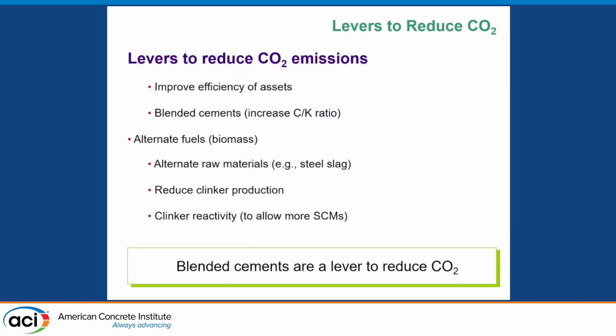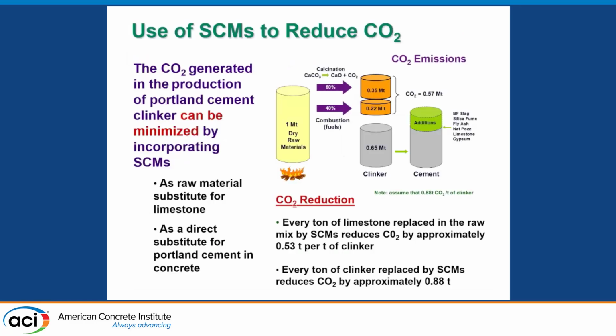Some of the levers we've seen from the cement manufacturers are to improve the efficiency of their assets, use biofuels, use blended cements, and reduce clinker production. The way they do this is basically by the removal of portions of the cement and by using additions, whether it's blast furnace slag, silica fume, fly ash, natural pozzolan, and so forth. That is what's added into the finished product. Now it can be blended, or as we know as producers, it can also be done at the plant.